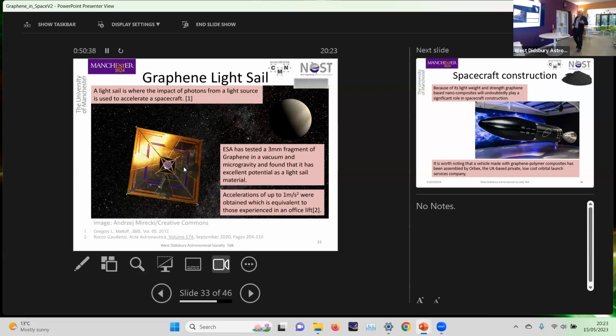The sort of accelerations that are achieved are not high. A meter per second squared, that's about what you get in an office lift. But remember, as long as the light's shining on it, it's accelerating. So you can reach quite high velocities if your craft is light enough. It mustn't be heavy. So graphene would be very useful.